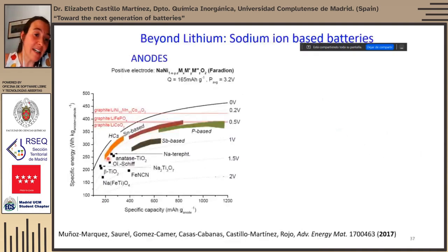These materials actually have relatively good performance, although if we look at this plot of specific energy, considering the weight of the anode and cathode material, for a positive electrode composed of a layered sodium oxide by the British company Faradion, taking into account the specific capacity of each anode material and the voltage at which the reaction takes place, which is indicated by these dashed lines, we can see which is the specific energy of the system. And we can see that actually sodium-ion batteries do have a slightly lower energy and specific energy than lithium-ion batteries,